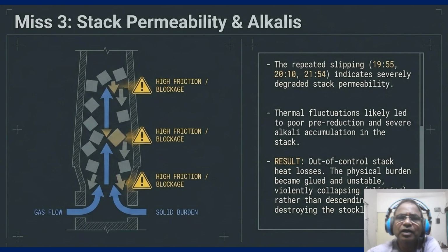So the so what factor here is the total loss of the stock line. When the burden becomes glued and then violently collapses, it destroys the gas distribution and puts out the fire in the hearth with a mass of cold unreduced material. So you must monitor your eta CO and top gas to ensure the burden is properly pre-reduced before it ever hits the bosh.